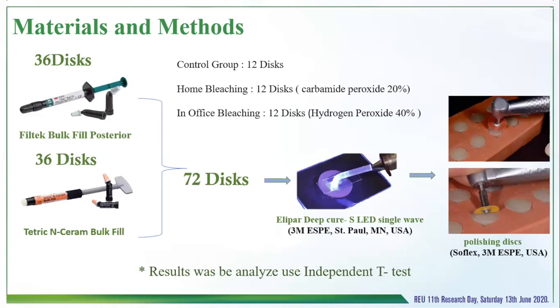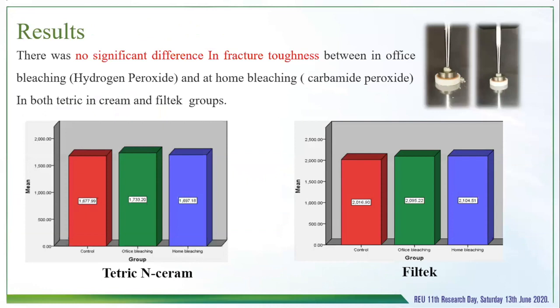36 specimens of each composite disc were finished and polished using Sof-Lex, divided into 3 groups for each bulk fill material: 12 discs for the control group, 12 discs for home bleaching, and 12 discs for office bleaching. To get an accurate result, according to the statistician's advice, the minimum sample that could be used in every group is 10, but in this study, 12 discs were used to assure the sample is normally distributed. The result was analyzed using independent t-test. About the result, no significant difference in fracture toughness between office and home bleaching in both Tetric N-Ceram and Filtek.